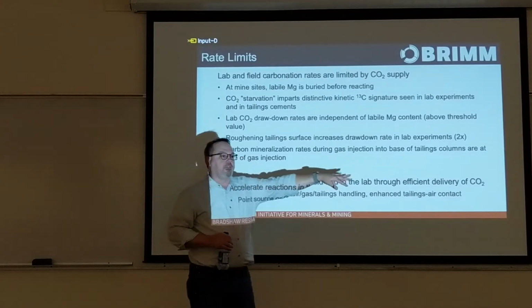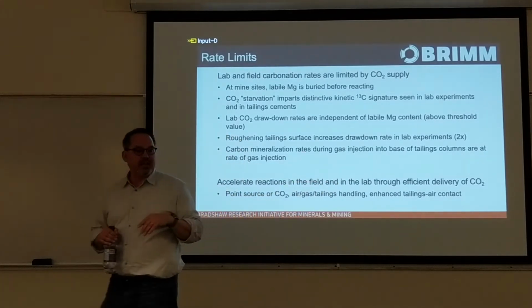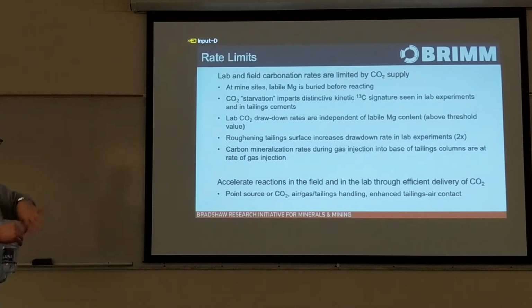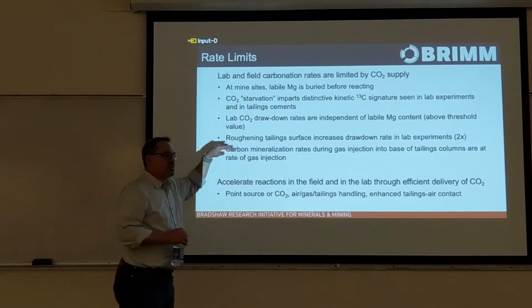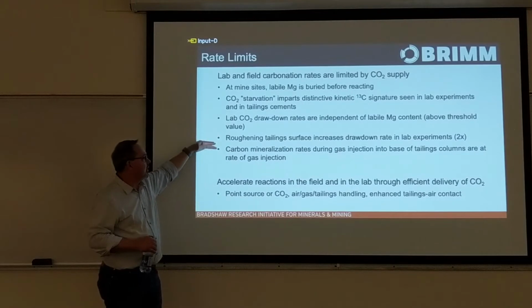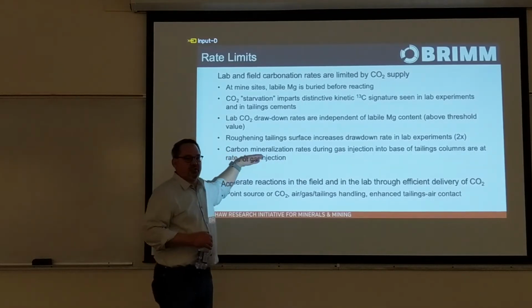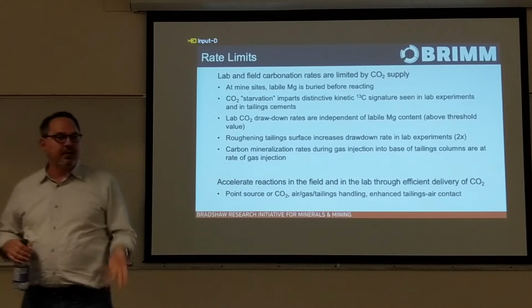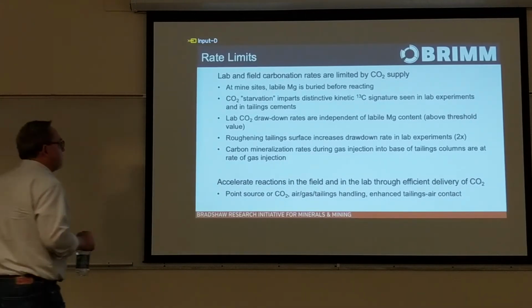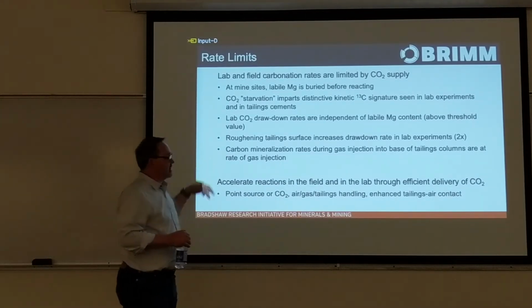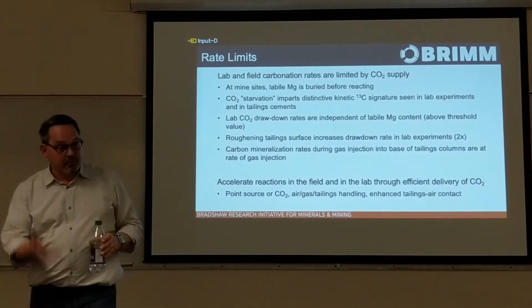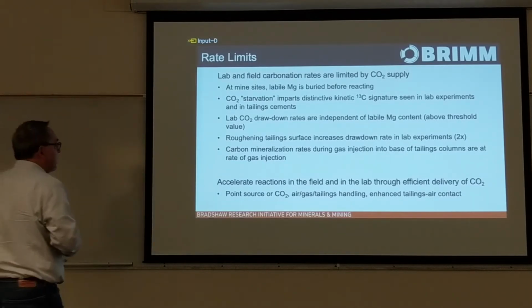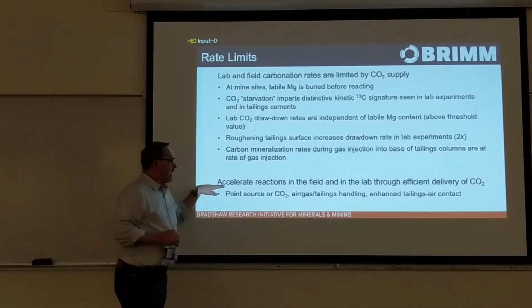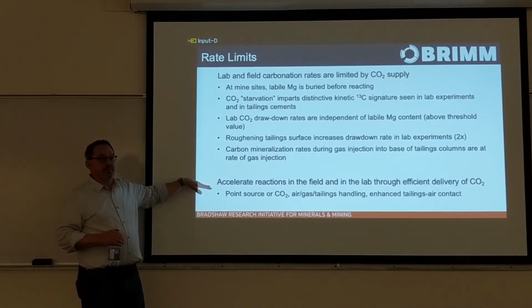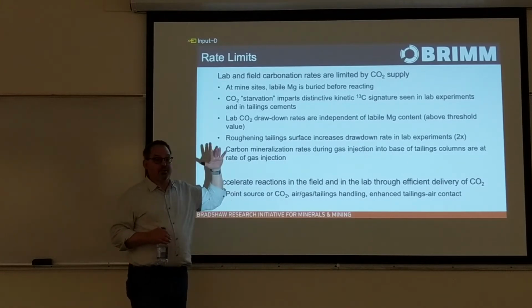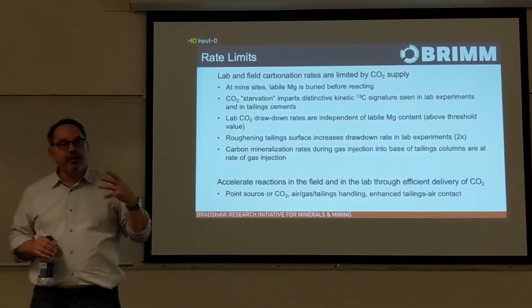If we take these materials and roughen them, basically till the surface of tailings, we can double the uptake rate, because we have essentially more exposed surface in direct contact with air. And when we run injection into sort of meter-sized columns of tailings to look at how flue gas might react, our rates are essentially the rate of carbon we're supplying at the base of the column. So there's a whole bunch of ways that we can enhance delivery of CO2, and that will then allow us to accelerate things, and we'll accelerate to the point of mineral reaction.